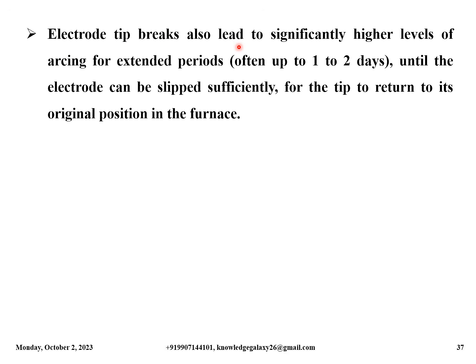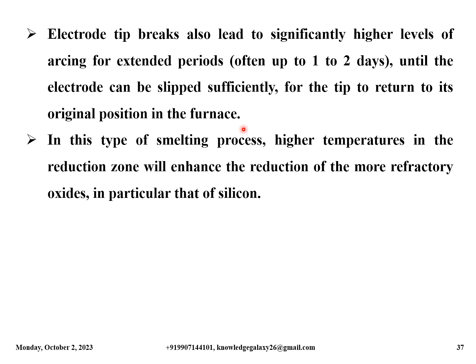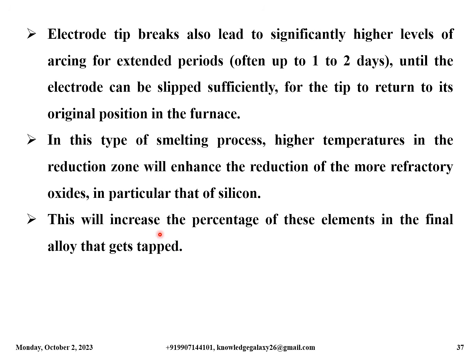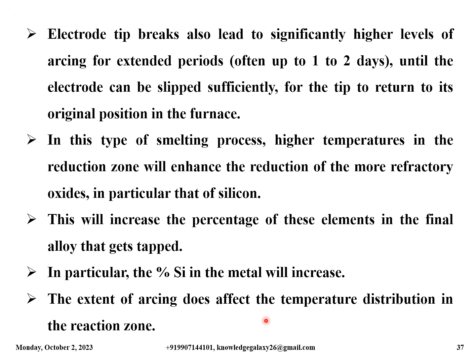Electrode tip breaks also lead to significantly higher levels of arcing for extended periods, often up to 1 to 2 days, until the electrode can be slipped sufficiently for the tip to return to its original position in the furnace. In this type of smelting process, higher temperatures in the reduction zone will enhance the reduction of the more refractory oxides, in particular that of silicon. This will increase the percentage of these elements in the final alloy that gets tapped. In particular, the percentage of silicon in the metal will increase. The extent of arcing does affect the temperature distribution in the reaction zone.